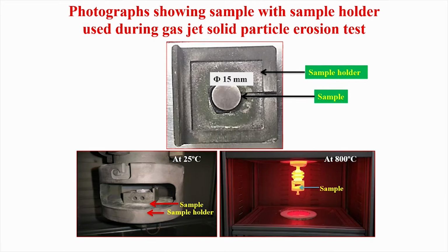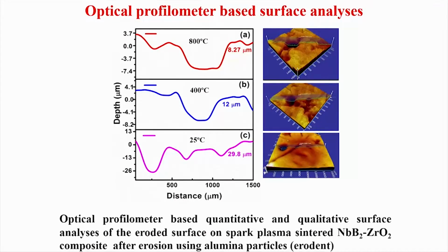So, this is the 15 millimeter diameter sample that we typically use, that is the top panel. You can see the sample holder, and the sample is embedded in it, and this is at 25 degrees Celsius. You can see through the glass the erosion experiments, and when the sample is red hot at 800 degrees Celsius, erosion wear is also possible. Erosion experiments can be conducted at 800 degrees Celsius as well.